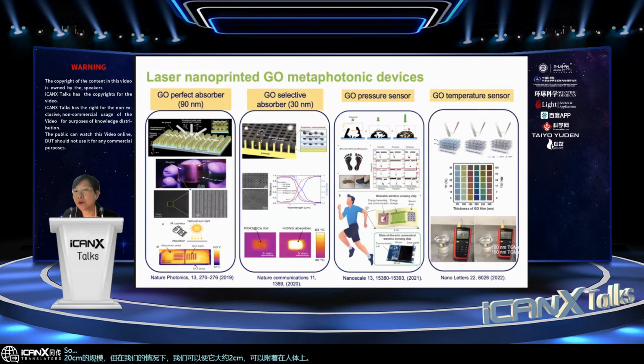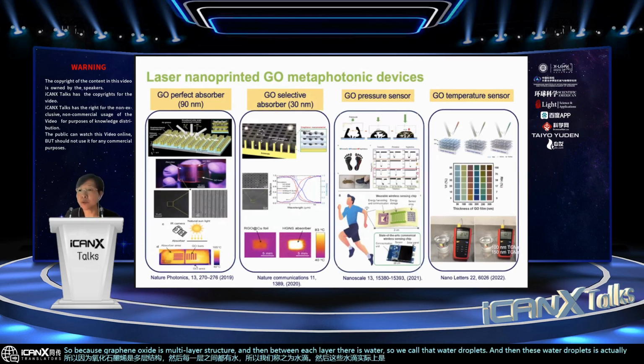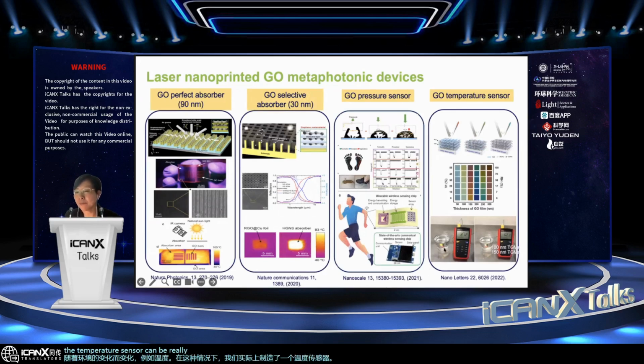So because graphene oxide is multi-layer structure, and then between each layer, there is water. So we call that water droplets. And then these water droplets is actually changing in response to the environmental change, for example, the temperature. So in that case, we actually made a temperature sensor. The temperature sensor can be really interesting because it changes color when the temperature is increasing or decreasing. So such kind of sensor can be attached to the mobile phone, for example, to kind of warn people when the temperature goes too high.